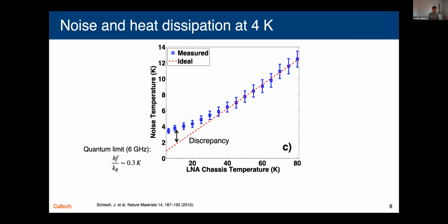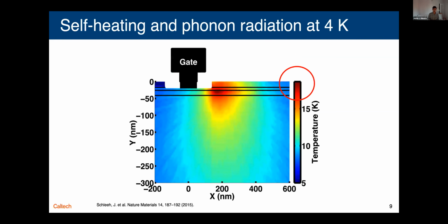So some time ago, we did these experiments where we're measuring the noise temperature versus the physical temperature of the amplifier. And you observe that there's this discrepancy at low temperatures where the noise temperature is supposed to be something less than a Kelvin, but it actually saturates instead experimentally to something around 3 or even 4 Kelvin. And of course, this is a significant problem. So we thought about this, and eventually we think we've figured out that the origin is due to self-heating.